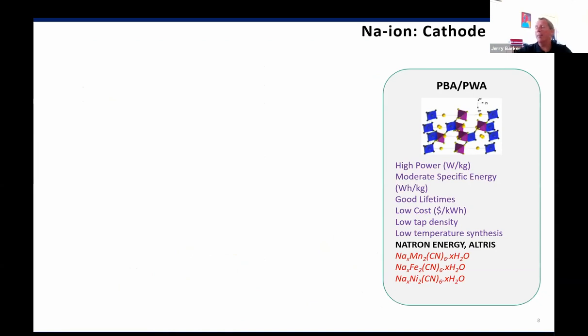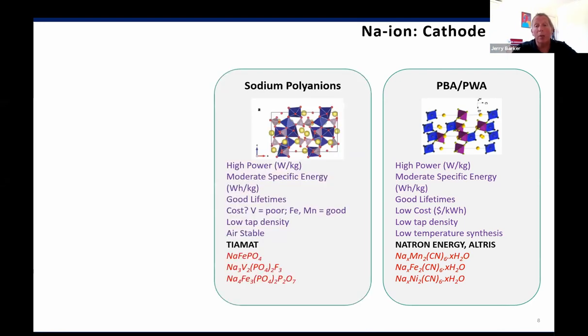Cathode choices, just like in lithium ion, we can differentiate our cell chemistries by our cathode choice. So as I said before, one option is using Prussian blue analogs, or for that matter, Prussian white analogs, but cells made from those have fairly moderate energy density. They have good power, and you can make them at a low temperature. So that means it's generally quite good for cost, but they're only really good for low energy, high power applications. There's a couple of companies working on that in the world, and I'll come back to that in a few minutes.